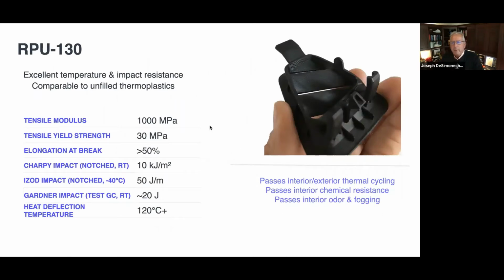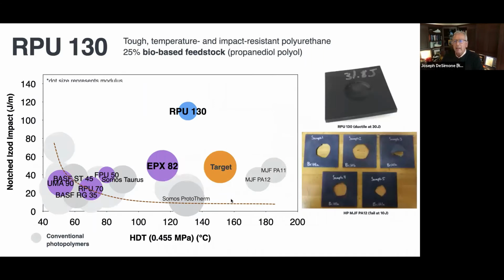This is a rigid polyurethane with a Tg of higher than 120 degrees, high modulus, amazing tensile strength, and ductility. This has got a behavior that looks a lot like a thermoplastic. And so look at these comparisons of notched Izod versus heat deflection temperature. The RPU 130 is sitting here, and this is a placard that got impinged by a projectile, and you can see ductile deformation. These are some placards made by SLS in a fracture, a polyamide SLS system.